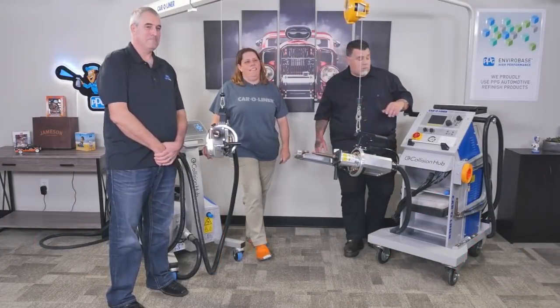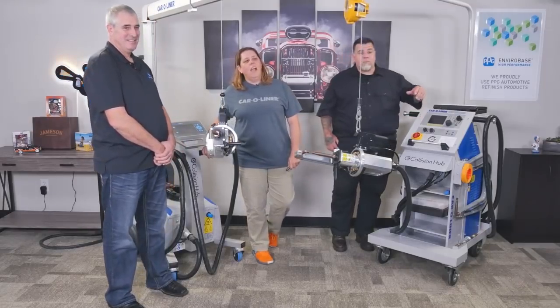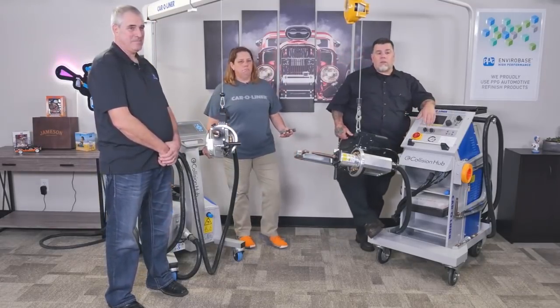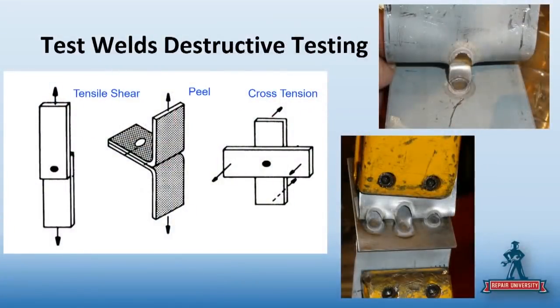R9, yep. Makes it so much easier for the R9. All right, so here's some more of the tears. Okay, well, this here is a peel test, and the top photo, although it tore out a very big hole, you shouldn't have one weld because you have to shunt your first weld. That'll be your weakest weld, and then you actually really test in the second weld.